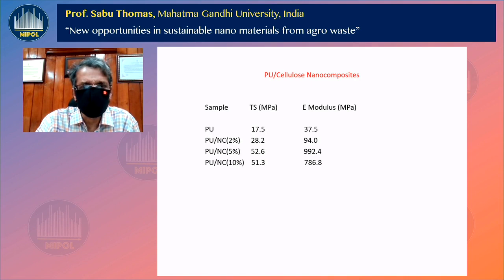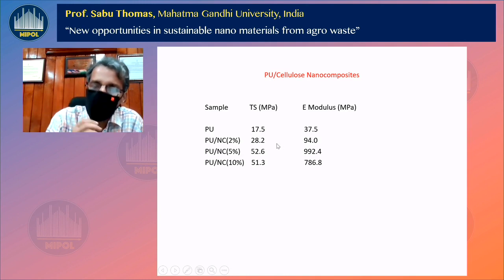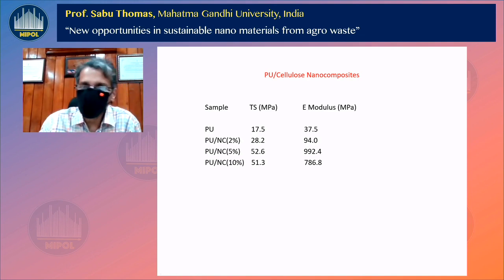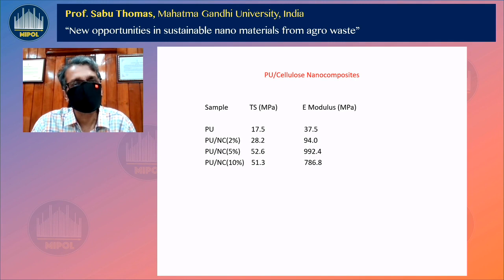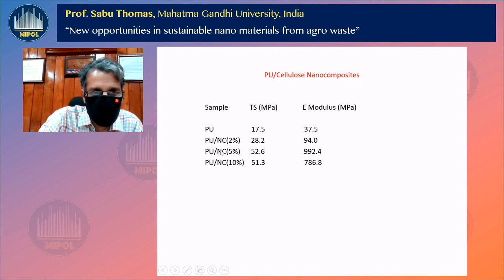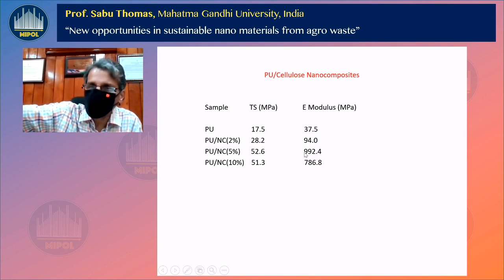Let me show you another important work we have done with Sao Paulo University in Brazil, because we had a long cooperation with them. My Brazilian counterpart is very active in making polyurethane. Look at the PU made by my Brazilian colleague, the strength, the modulus. We thought of reinforcing this with cellulose nanocrystals produced from pineapple leaf fiber. See, look at this slide. If you put 5% of nanocellulose, the strength becomes 52.6. And you see a quantum jump in modulus, 37.5 becomes 992.4. Remarkable increase.